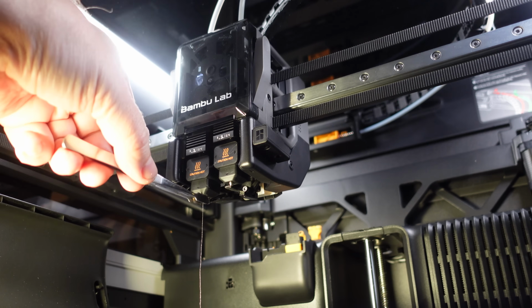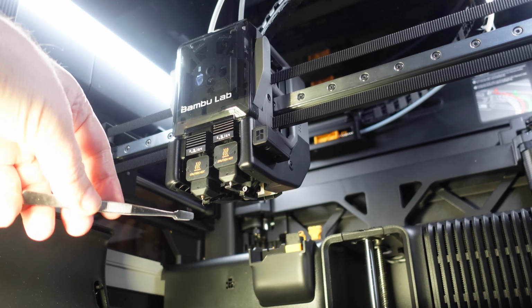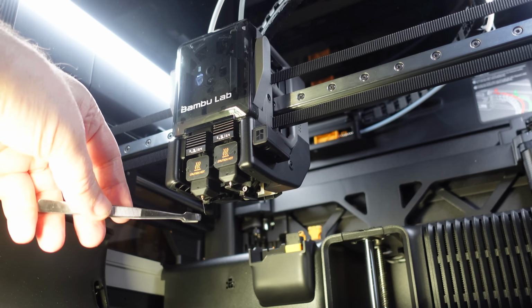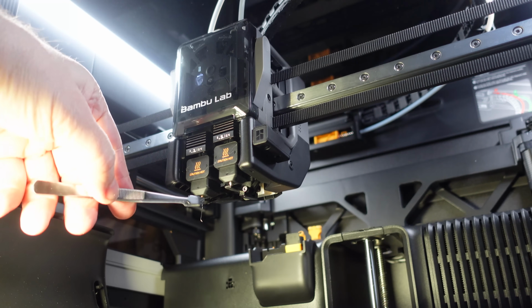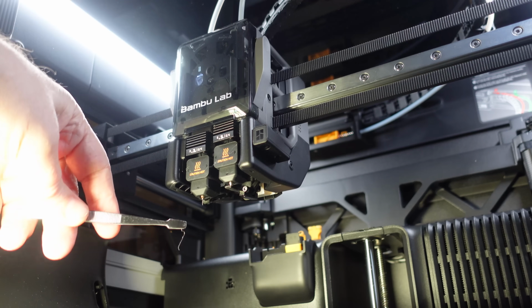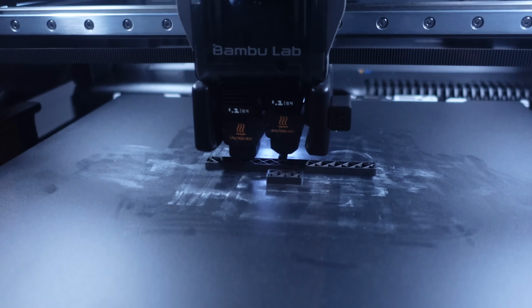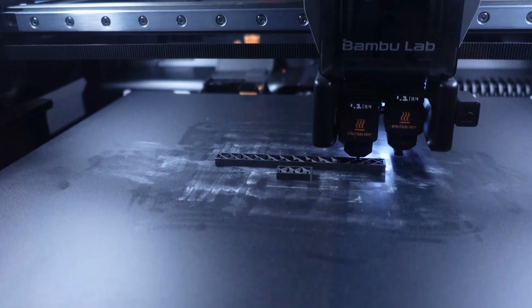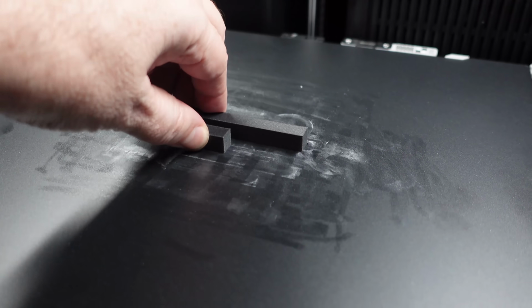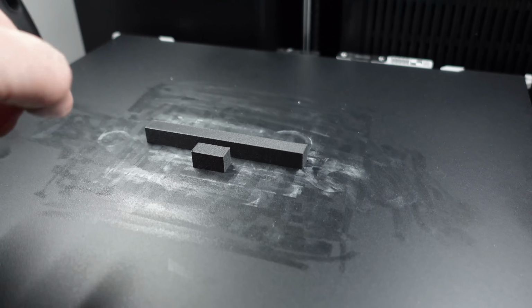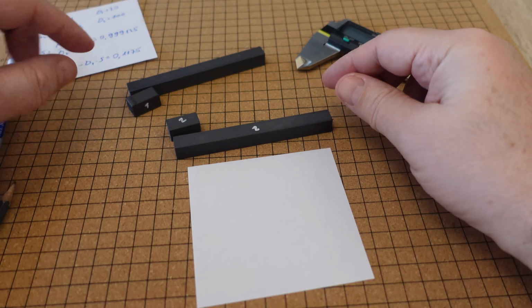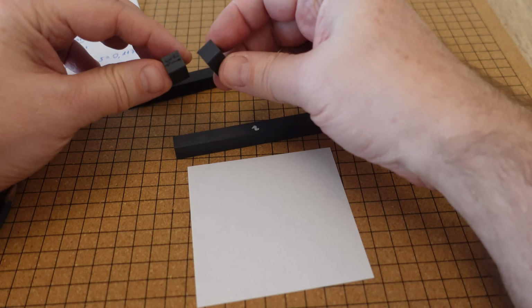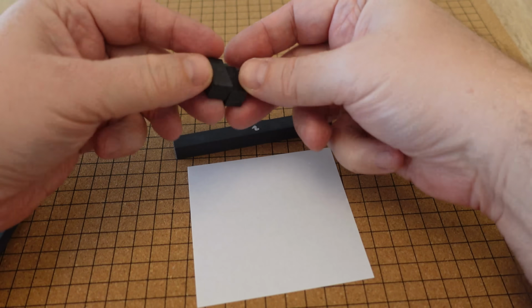Again I am checking the oozing, and I can see that the oozing is still here. It is reduced a little bit, but it still appears, so looks like here we have the oozing even with relatively dry filament. And again reprinting those objects for the measuring. Engineering plate with the glue, the adhesion is great. And now let's measure these test objects. Now there is no stringing, for example, like you can see here.